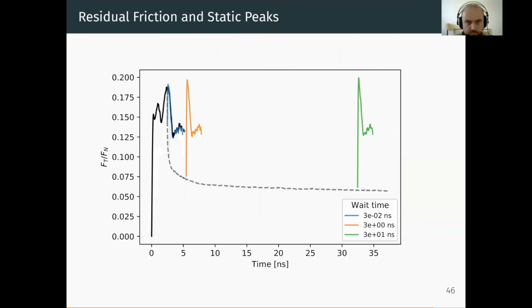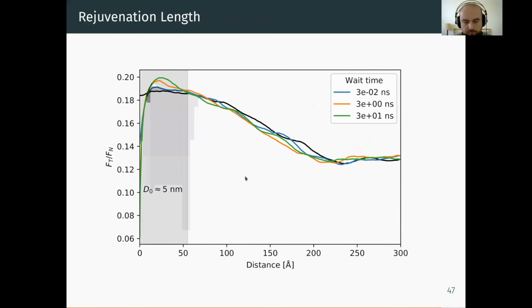That's the black curve. At some point of this sliding phase, I stop pulling on the spring, and then I let the system relax, and I have a relaxation in the tangential force. And I can see that I relax towards a value that is non-zero, just like in the experiments. And during this simulation, I restart the sliding process at different waiting times. Those are those colored curves here. And what I do is I look at specifically the transient regime, what happens really at the peak here. You can already see that there's a bit of an increase in the peak, but this is more apparent in this figure, where I plot everything as a function of sliding distance.